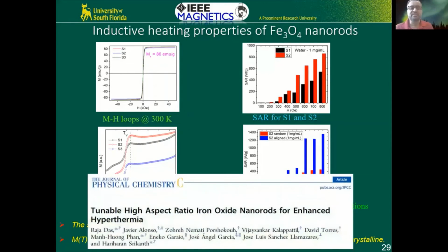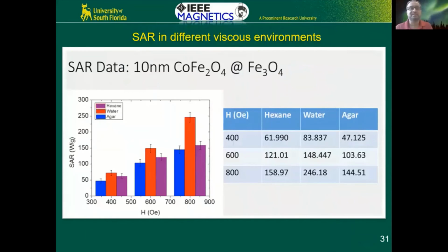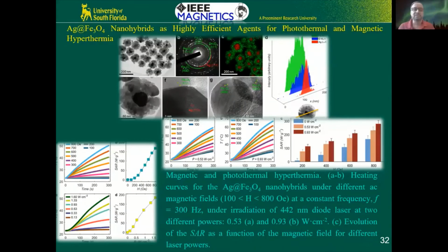I'm almost ready to finish here. I'm going to skip these things. And yeah, we also did some dual functional systems. For example, remember the configuration that I talked about? Here we can make nano clusters. We can take gold or silver nanoparticles, gold is even better, and use them as a seed, and you can have magnetite growing around them, forming these nano flower structures. Now these are bifunctional because the gold surface is also exposed and the magnetite surface is also exposed, so you can use them for different functionalizations.